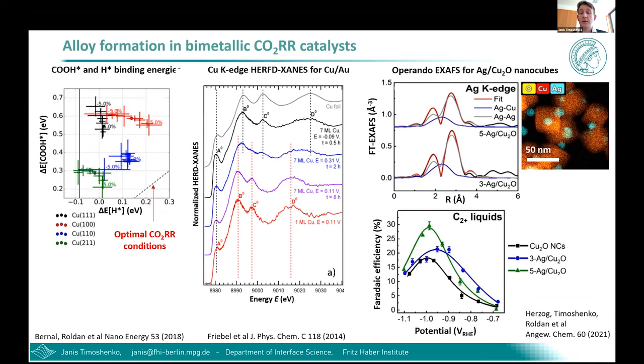And EXAFS, or X-ray absorption spectroscopy in general, is quite good at answering this kind of question. In this recent study, which focused on copper cubes decorated with silver nanoparticles, it was really demonstrated that silver-copper bonds are visible in EXAFS spectra, and moreover, these contributions are getting more pronounced under reaction conditions. And of course, it's also nice to see that the presence of the silver-copper bonds was nicely correlated with the enhanced activity of CO2 conversion to multi-carbon liquid reaction products.